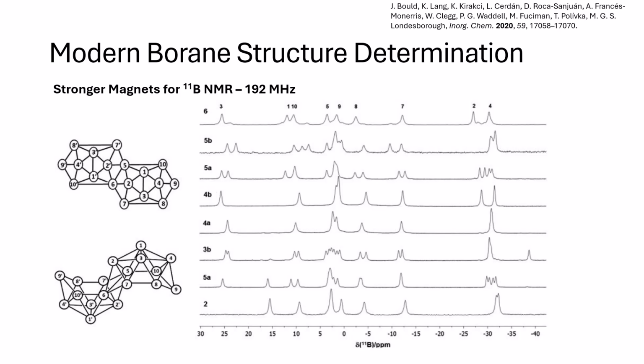Modern advances in NMR instrumentation allow for better boron structure determination. Shown here is an example in which a stronger magnet, roughly 10 times the strength of the magnets we've previously seen, is used to determine boron structure. In this case, the splitting pattern of the boron NMR is really well resolved, and it allows us to determine the structure of complex boranes like the structure shown on the left.